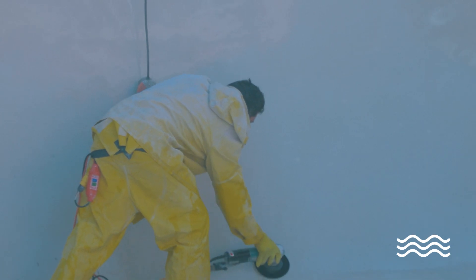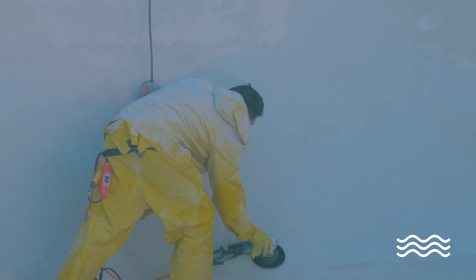That's correct. So first off, tell us the problem with the pool behind us. This is a pool you plastered some years ago. Yeah, this pool is a job we did 14 years ago. It was a standard plaster and we put a pozzolan in it back when the pozzolans were positive coming out of the industry. The original owner sold the house four years ago. It's a 14-year-old plaster job, and the new owner started using a floating chlorinator with trichlor. The cyanuric acid got away from him — he didn't quite understand that — and so it got into very negative indices on the saturation index.